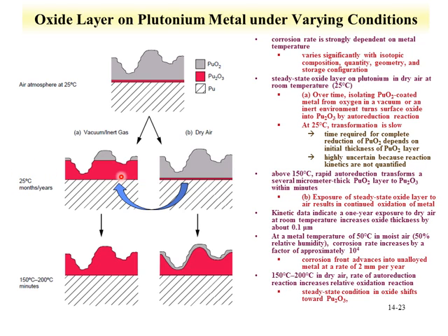over a long period of time is an increase of the growth of this Pu2O3 layer. Under dry air, it's a very thin layer. However, under the inert atmosphere, this layer can grow into a rather large layer. If the temperature is increased, what we see occurring is for both systems, the Pu2O3 layer can be very large. In the dry air, it goes to a steady state, whereas in the vacuum and inert gas, this phase can be the dominant oxide phase.